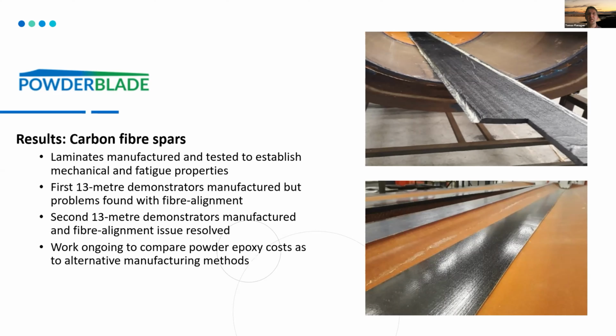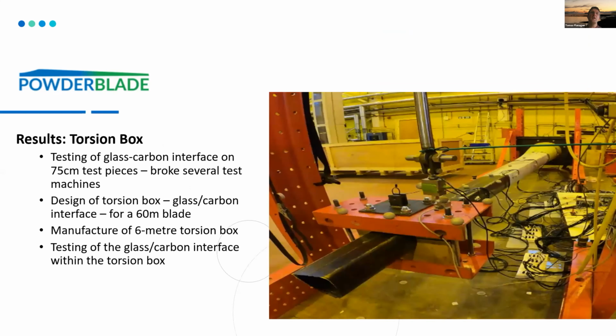So I guess technically we know that the solution is pretty good, and it's about building the business case around it. So then we built a torsion box, which was a scaled down version of a 60-meter blade, which was designed by Suzlon. So it had a glass fiber root and a carbon fiber spar, and a transition from glass to carbon. And that was tested at the University of Edinburgh, and we got pretty good correlation with the analysis that we've done.